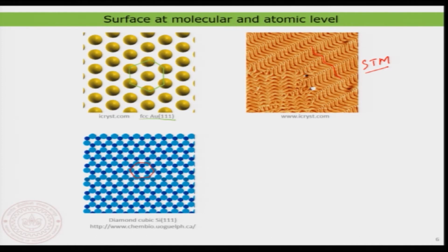So as expected, here you would have expected to see basically a 3-fold symmetric arrangement of the atoms, but instead the real microscopic image of a gold 111 crystal looks entirely different. Why is that? It is actually due to the fact that no surface is actually stable, and therefore it undergoes something called a reconstruction, and due to the reconstruction the atoms on the surface are rearranging and forming an extremely different pattern, which is known as a herringbone pattern.